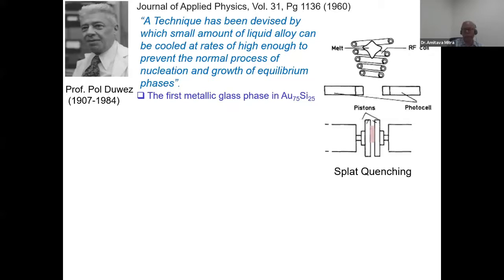This heat extraction from this forms a glass. So you can see once again, an alloy which is heated by RF coil, and when it melts and is superheated around 50 to 100 degrees, it drops from there, it comes here, and the piston comes together and takes heat from both surfaces.